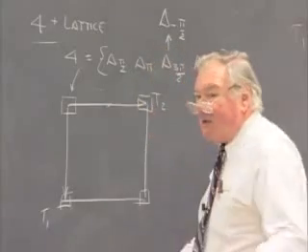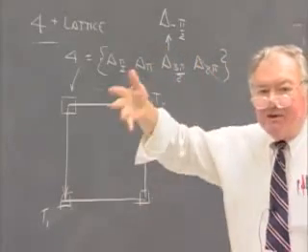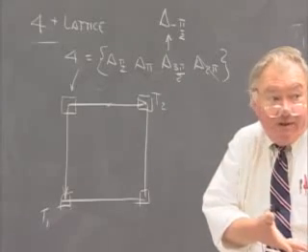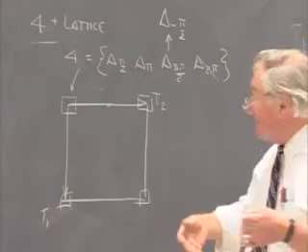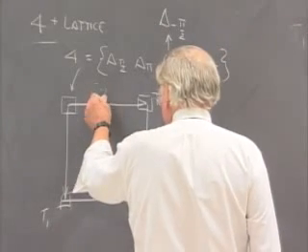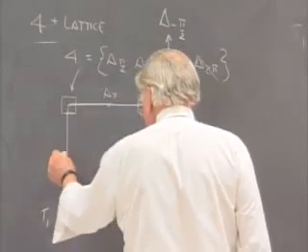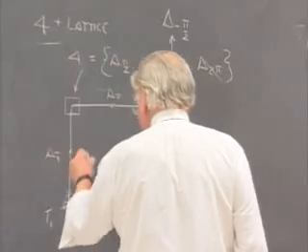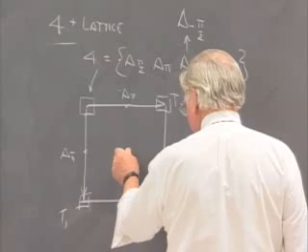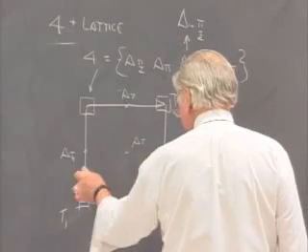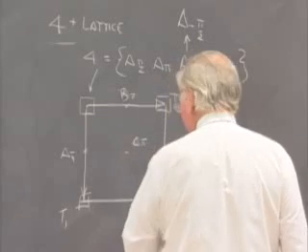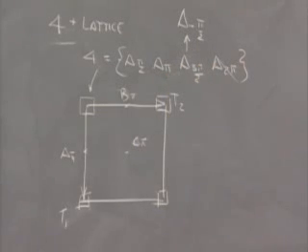We've already done this, A pi, in deriving P2. And that's the nice thing about this derivation. It's going to snowball because as the symmetry gets higher, we've already done the work for the subgroup that contains the elements that are present in the higher symmetry. So we'll get an operation A pi here. We'll get an operation A pi here. And if we take the diagonal translation T1 plus T2, I'll get the operation A pi here. Or I should probably call them A pi, B pi, and C pi to indicate that these are different twofold axes.